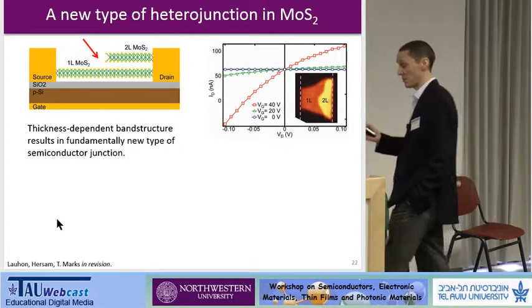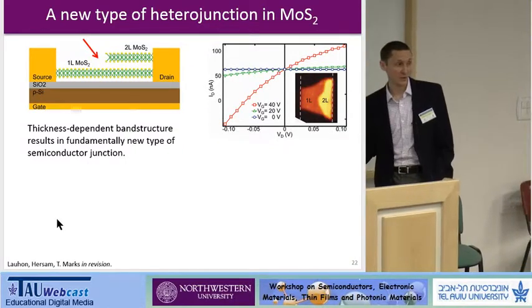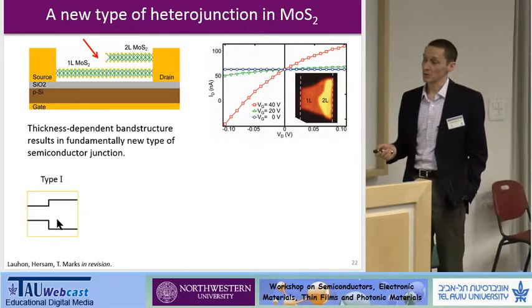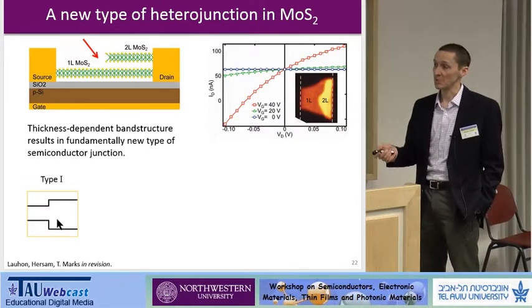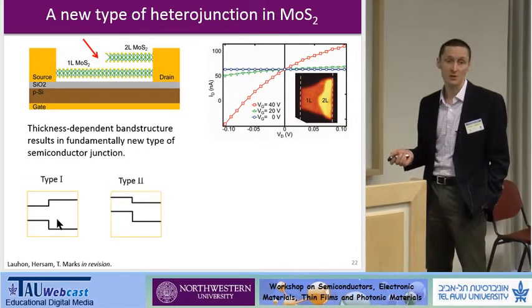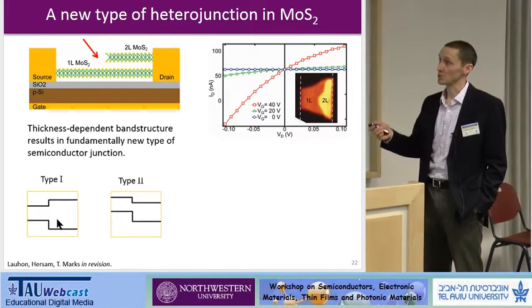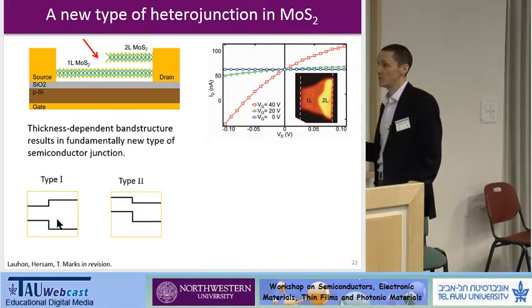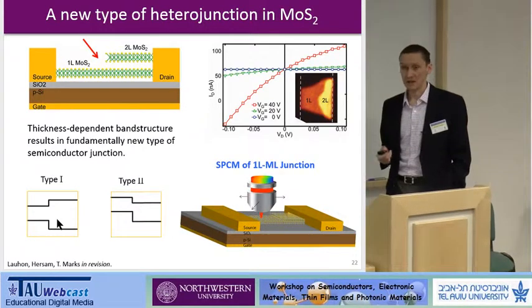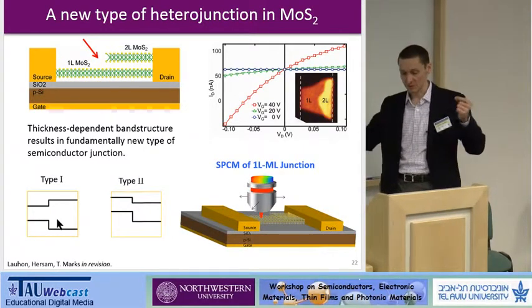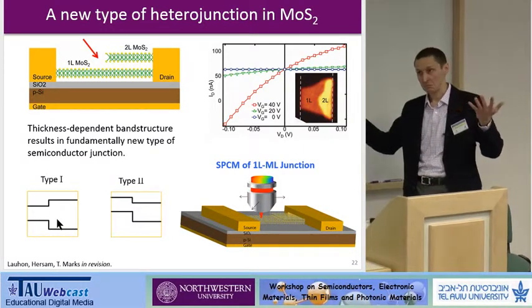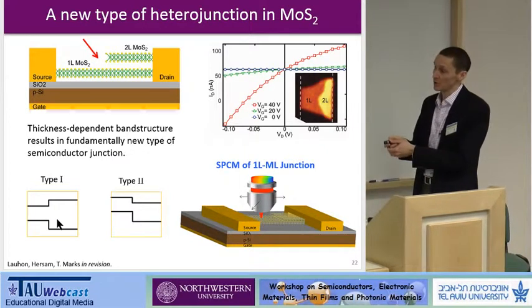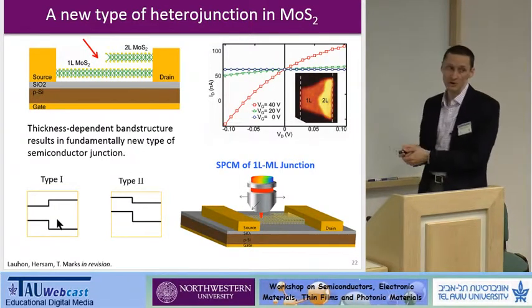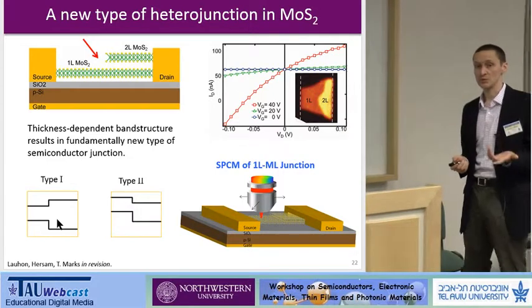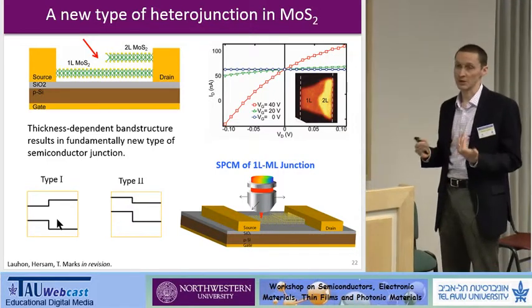Okay, so whatever's in the middle there at least has rectifying characteristics. But what we don't know is whether the band alignment is type 1 or type 2. Either one might produce such a rectification. So what we've done is to apply scanning photocurrent microscopy, where instead of just measuring a current and a voltage in the dark, we measure current and voltage as we scan a laser across the device and look at the response of the junction distinct from the channel or the contact.